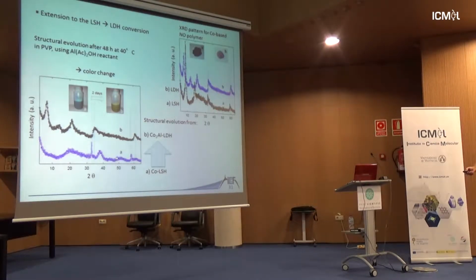And that you can tell because the color is completely different. You have the blue color LSH because you have octahedral and tetrahedral cobalt. That's completely consistent with the color change between LSH and LDH. And at the end, you have the ingress of aluminium 3+ into the LSH by dissolution and precipitation, and you form the LDH.